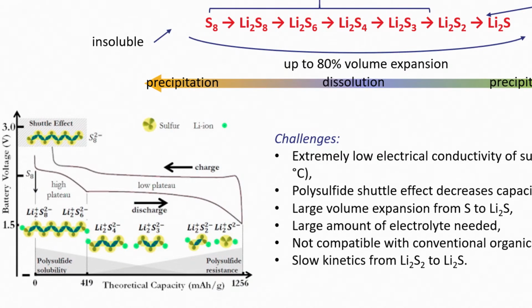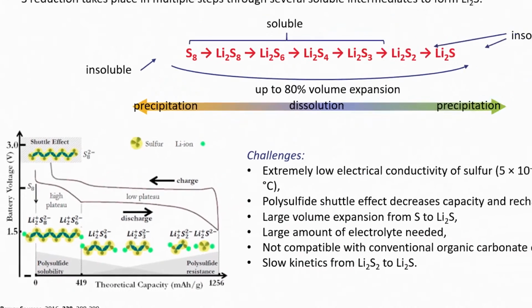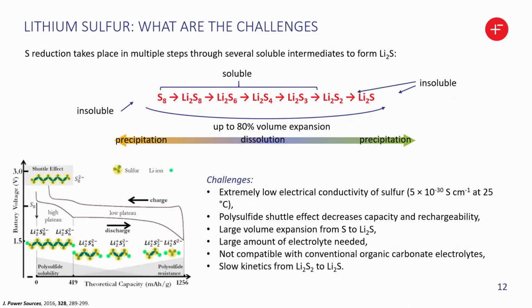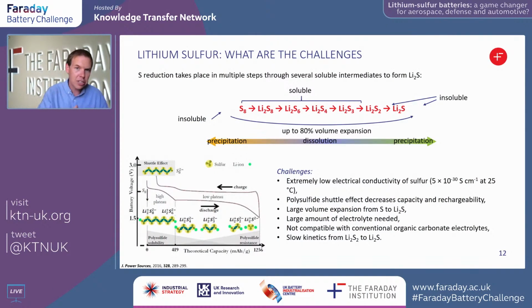The graphite negative electrode in the lithium-ion battery acts as a host for those lithium ions, but actually from one cycle to the next, as it accepts and then releases those lithium ions, there's not a huge physical change to the graphite electrode. By contrast, within the lithium-sulfur system, as the sulfur begins to react with lithium during those charge and discharge reactions, it actually becomes soluble. So we get a transition from a solid electrode into active materials that are soluble within the electrolytes.